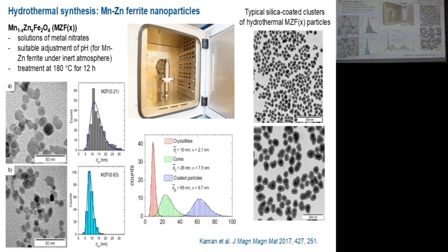And so during this adjustment of pH, adding sodium hydroxide or adding ammonia, you will precipitate some complex hydroxides or some complex mixtures containing hydroxides and oxides of manganese, zinc, and iron. And then you will transfer this precipitate, this precursor, into your autoclave, and you will do the hydrothermal treatment. As I said, just at 180 degrees for 12 hours. And you can see the resulting particles here. So these are the bare particles. No surfactants were involved.